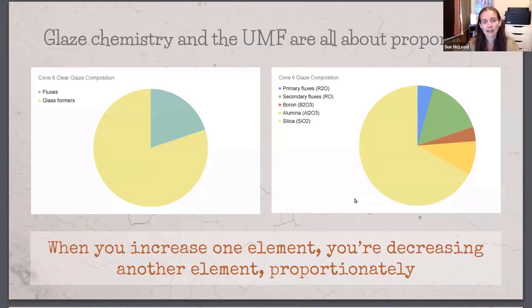So we add fluxes to bring down the melting temperature of silica and alumina to a temperature that our kilns will easily fire to, like cone 6, cone 10, cone 06, whatever you're firing to. Chances are your kiln will not reach 3,200 degrees Fahrenheit. So we need fluxes.